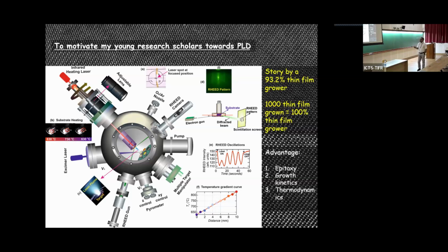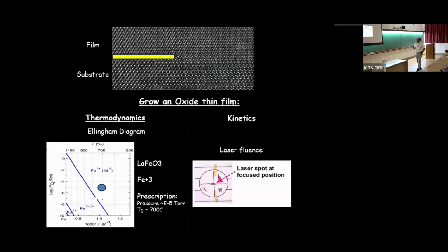And this system is typically equipped with a very fine technique called reflection high energy electron diffraction, by which you see some oscillation in the diffraction pattern. With the growing of the thin film and counting this number of oscillations, basically you can tell precisely how many monolayers have grown on top of this film. So the advantages: you can have epitaxial growth, you can use the growth kinetics as well as the dynamics and thermodynamics of the system. So actually you can grow extremely high quality thin films.